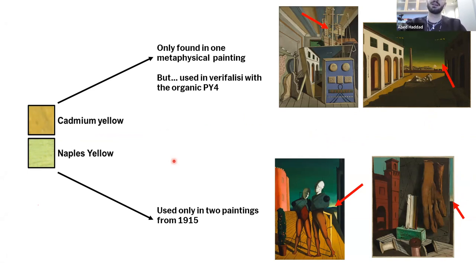Naples yellow, on the other hand, was only in two paintings from 1915, the Duo and Amusements of a Young Girl. And you can see, interestingly, he used that Naples yellow to create this very pale yellow horizon in the sky. So, similar use for this particular pigment. And Naples yellow is very easy to identify with XRF because antimony occurs very rarely in any other pigments, especially yellow ones.